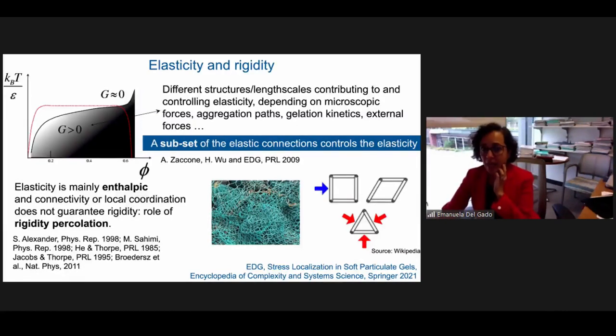depending on the condition in which the gelation is occurring in my experiment. And in these cases, we could show that if you, for example, consider some specific type of structures that can occur in this type of phenomena, like if the particles first lump together into clusters due to the attractive interactions, and then the clusters are elastically connected also between them, again because of particle-particle interaction, we could show that basically it's just a subset of all the elastic connections that you've built in the material, the cluster-cluster connections, that determine almost completely the elasticity of the system. So already there is a seed that a subset of the structure that I built ends up playing a major role in the mechanics.